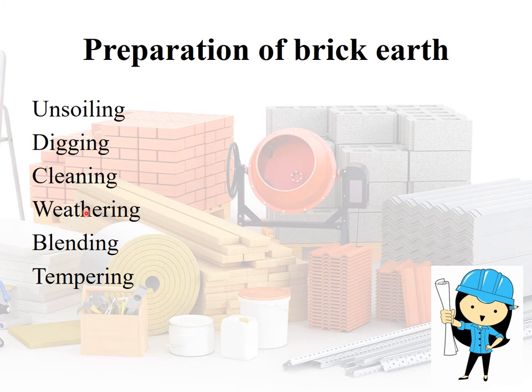Step four is weathering: spreading the cleaned clay material in layers of 60 to 120 cm thick for exposure to weather for several months. Step five is blending: mixing the brick earth material, water, and other ingredients to form good brick earth. Step six is tempering: using cattle or men to press and compact the clay material, making it ready for molding.